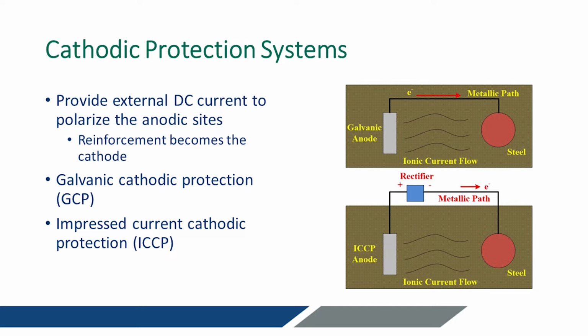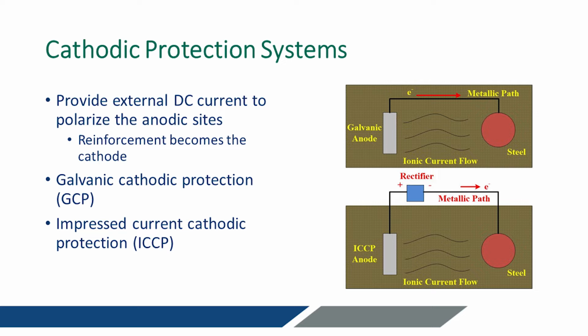Or maybe it has started, but it hasn't caused enough cracking and delamination of the concrete to warrant a patch repair. There are two forms of cathodic protection that people are generally familiar with. There's galvanic, which the last presentation was alluding to with zinc, where you take a sacrificial metal like zinc, aluminum, or magnesium, and in reinforced concrete, we only use zinc.